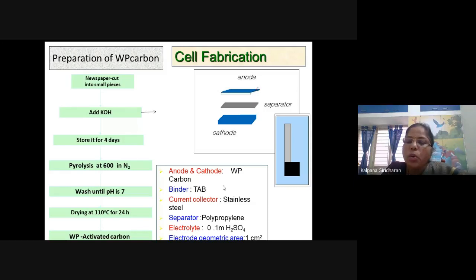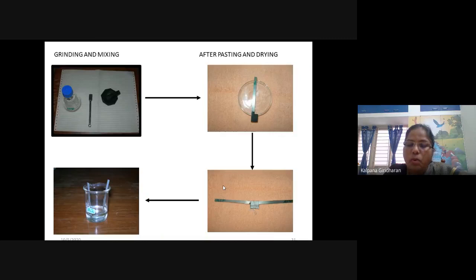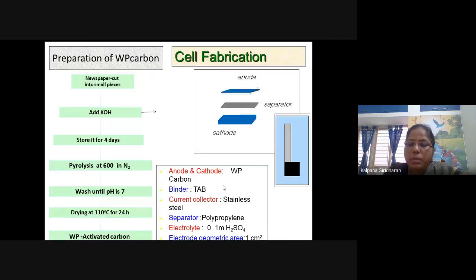We cut it into 1 centimeter by 1 centimeter geometrical area, and we sandwich the separator between anode and cathode. We have taken this activated carbon from waste newspaper as anode and cathode material, with a binder, a current collector of non-corrosive stainless steel 314, and a polypropylene separator, and we used 0.1 molar sulfuric acid as an electrolyte.